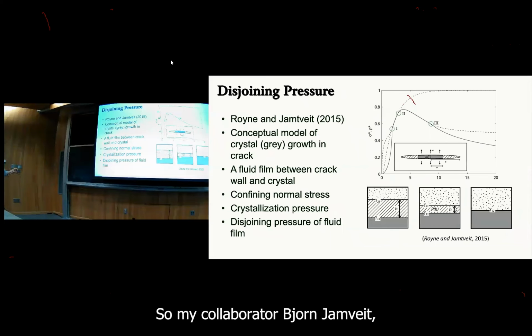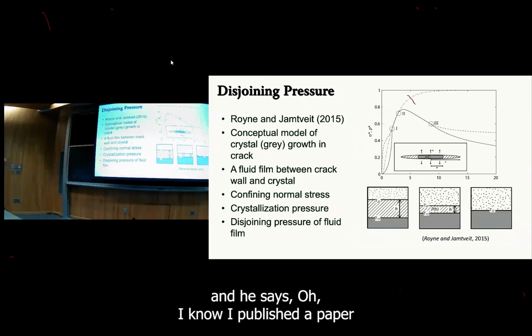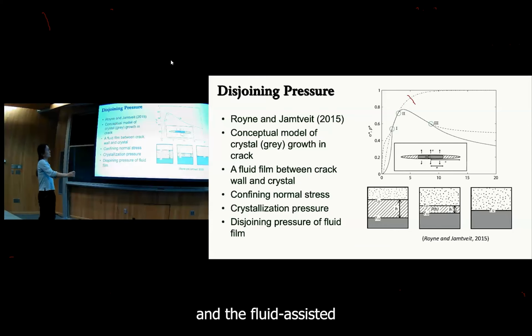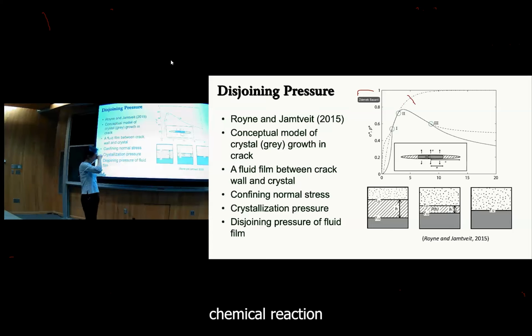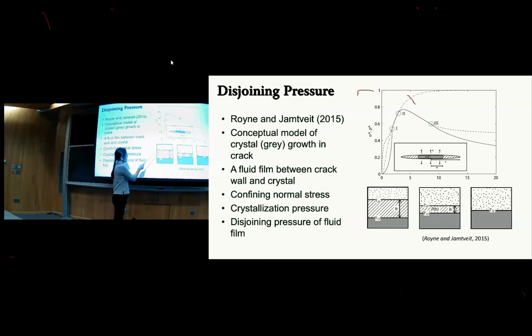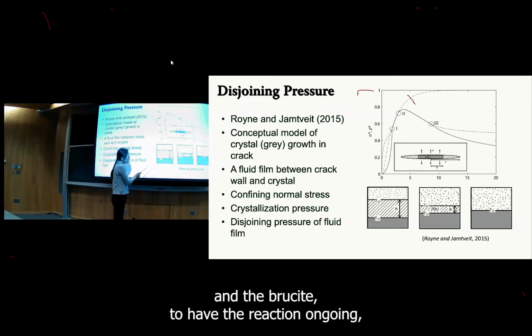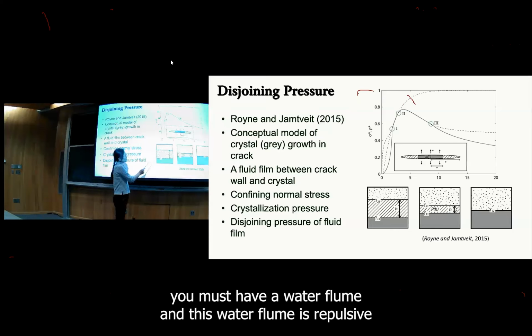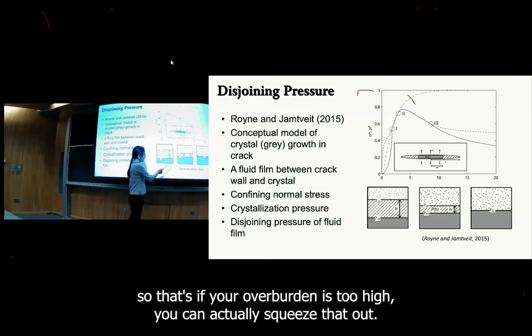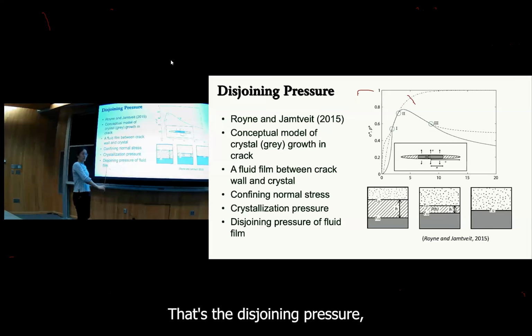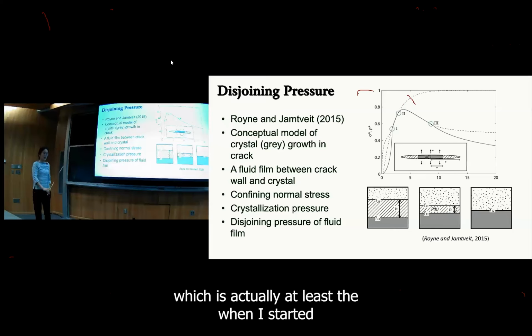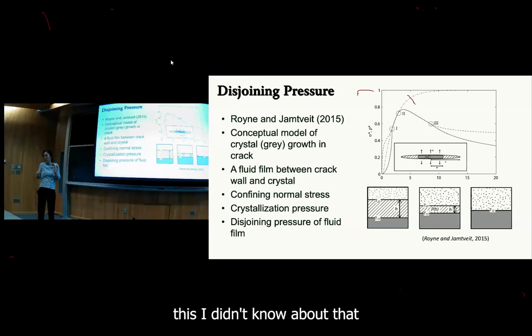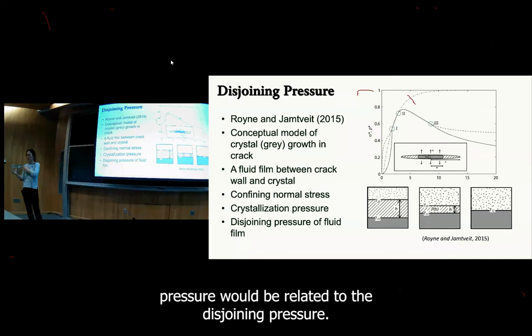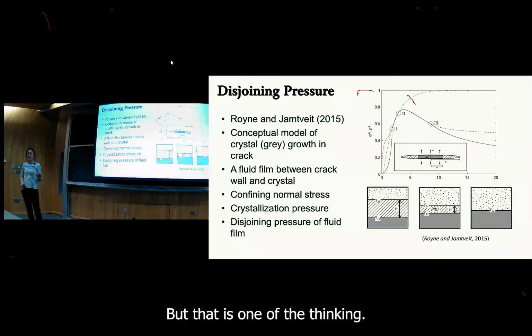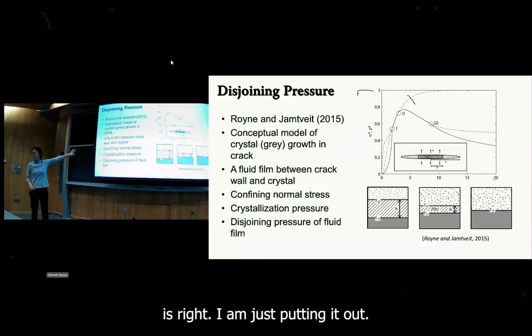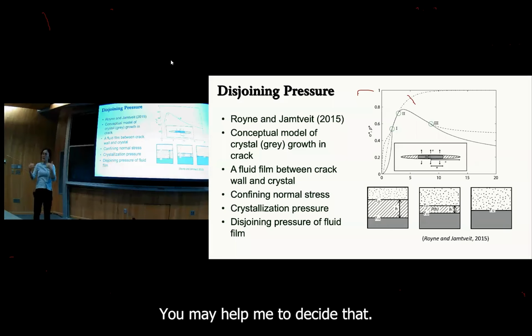So my collaborator, Bjorn Jamtveit, says, oh, I know, I published a paper and we talk about the crystallization pressure and the fluid-assisted chemical reaction, because between the periclase and brucite, to have the reaction ongoing, you must have a water film. But this water film is repulsive, so if your overburden is too high, you can actually squeeze that out. That's the disjoining pressure, which, at least when I started this, I didn't know about, and I didn't think the crystallization pressure would be related to the disjoining pressure. But that is one of the thoughts. I'm not sure this is right yet. I'm just putting it out so that you may help me to decide that.